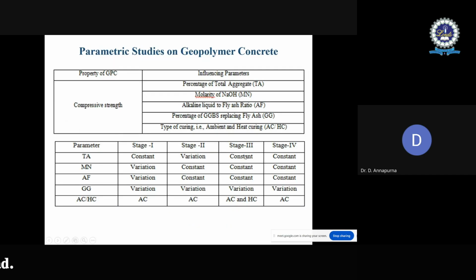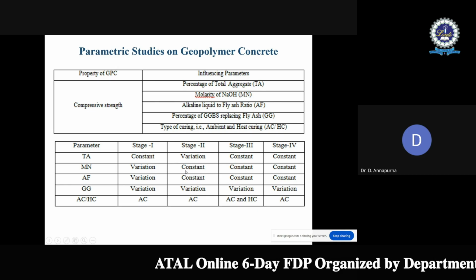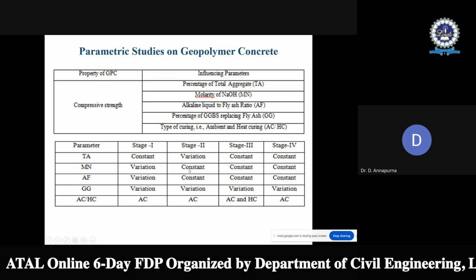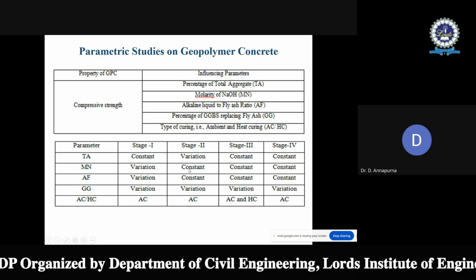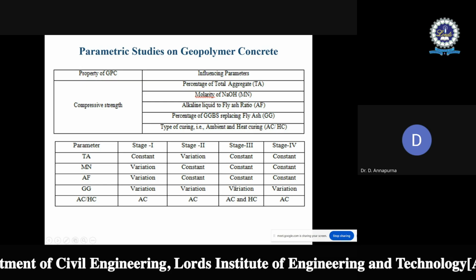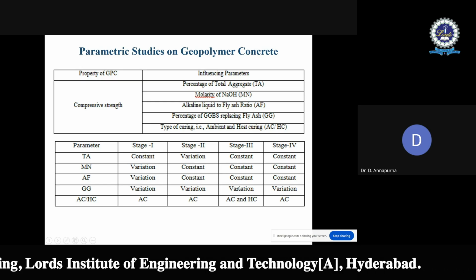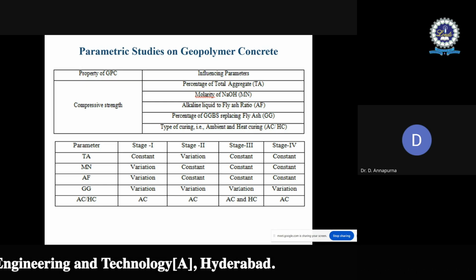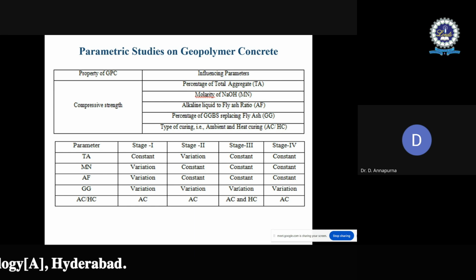That is the third stage. In the third stage, 70% of total aggregate is maintained. From the second stage, molarity and alkaline liquid to fly ash ratios are already maintained constant. Then the percentage of GGBS is improving the compressive strength, so that is the reason the same variation is considered again.